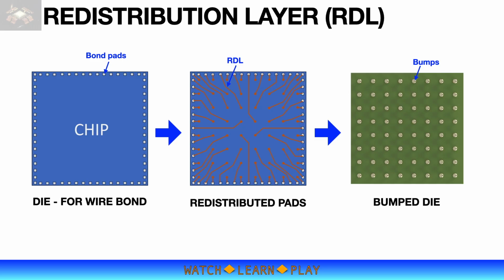Most chips are designed for wire bonding process, which means the bond pads are positioned on the perimeter of the die, closer to the leads to allow a proper wire bonding process with the shortest wire possible. When the same chips are used for flip chip configuration, the original bond pads have to be redistributed. The new pads are redistributed as evenly as possible on the top side of the chip, forming a cluster or array of pads for bumping process. This is done through the addition of a redistribution layer or RDL.